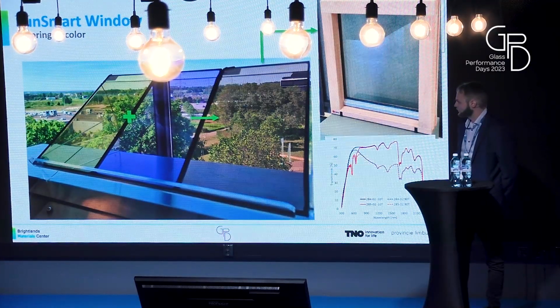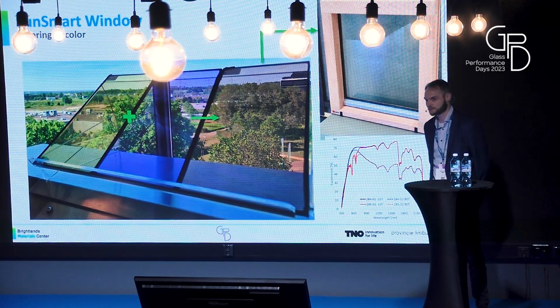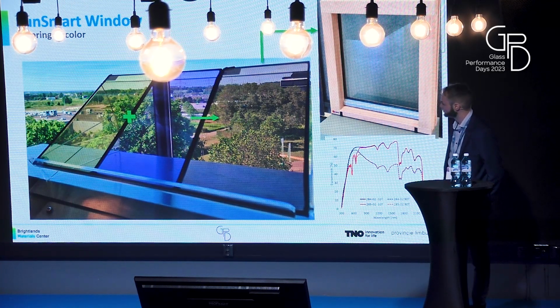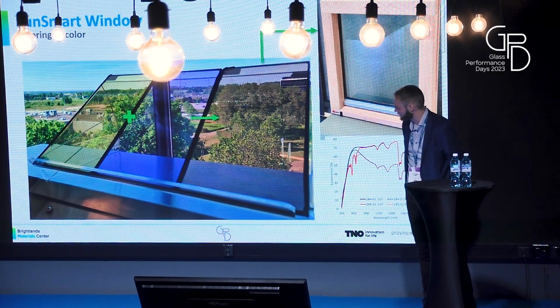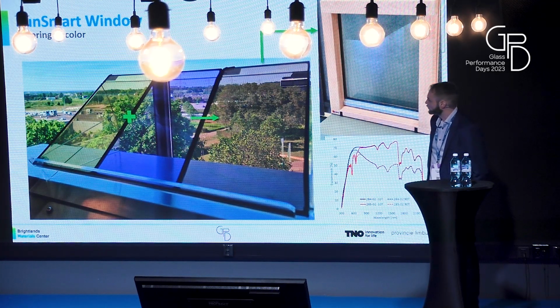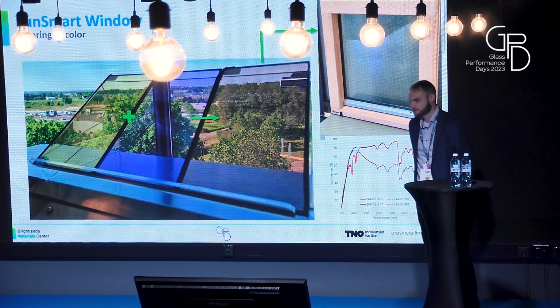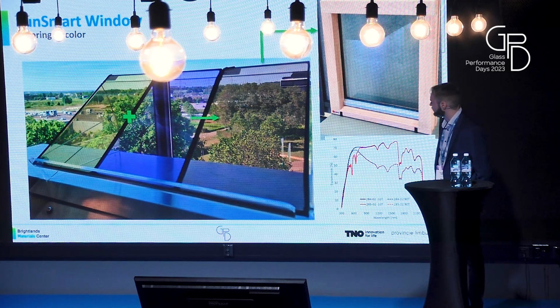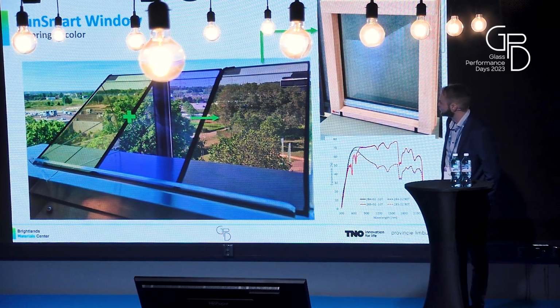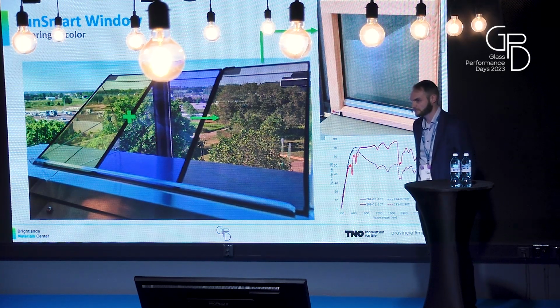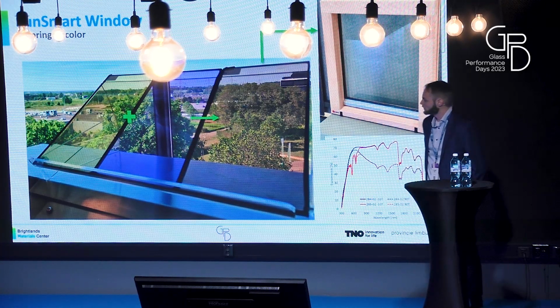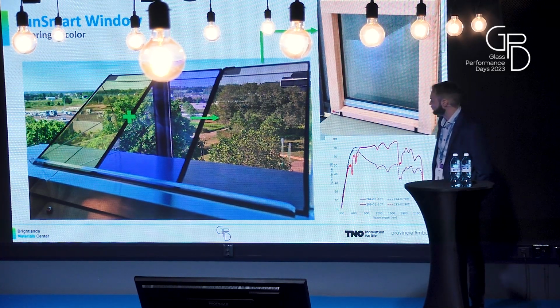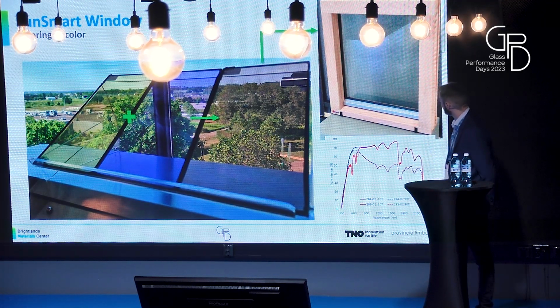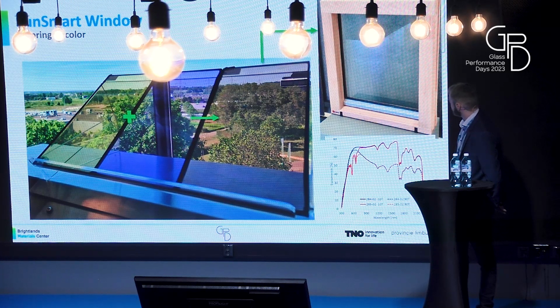If you are familiar with vanadium dioxide, you also know that the material itself intrinsically doesn't have the most pleasant coloration. It's slightly yellowish, brownish, which you see here on the sample on the left side. So we also worked on tailoring the color of the material to get to a more neutral color, and that you can do, for example, with PVB interlayers. There are colored PVB materials available, which you can tune to compensate or tailor the color to get to a more neutral coloration, which you see here on the right side, and also in this demonstrator, which really is very transparent and color neutral.